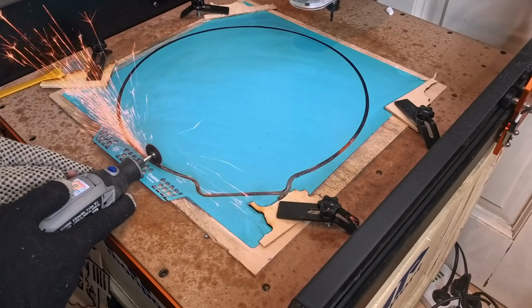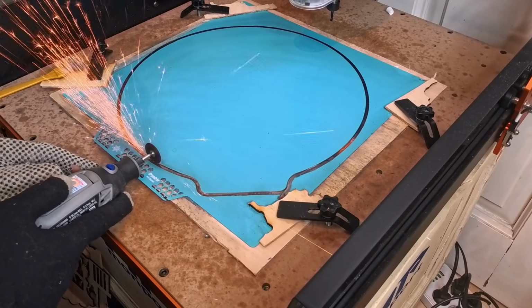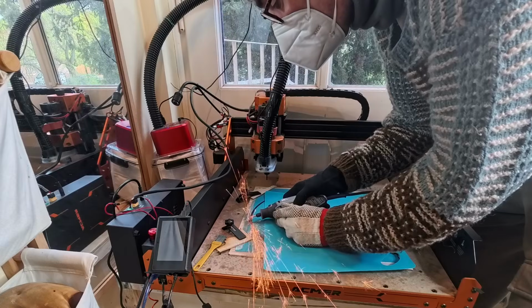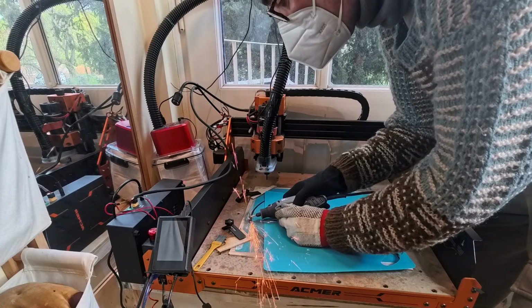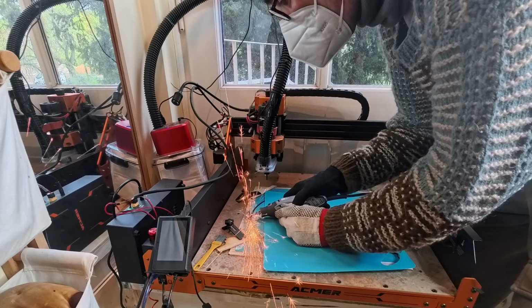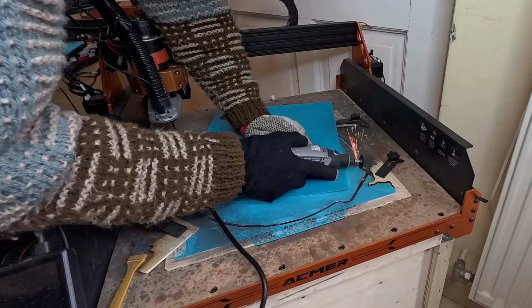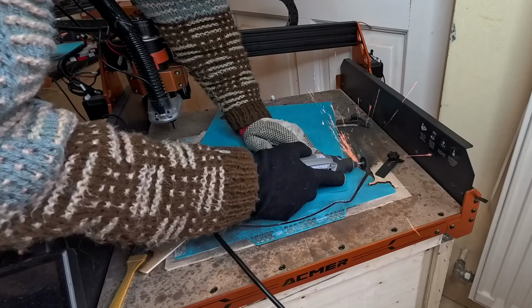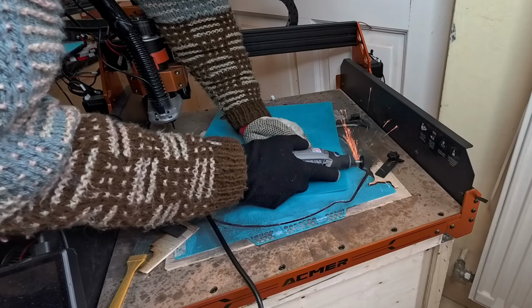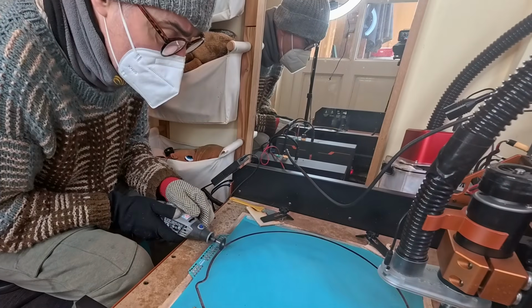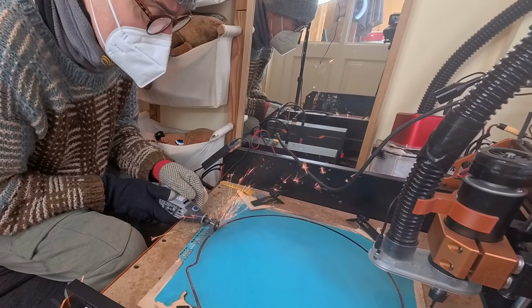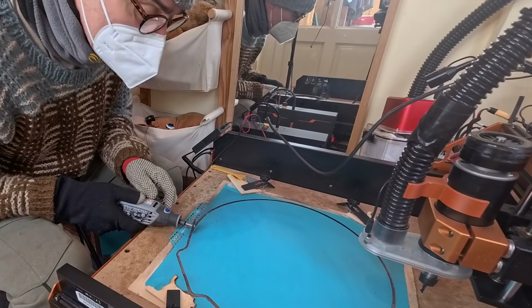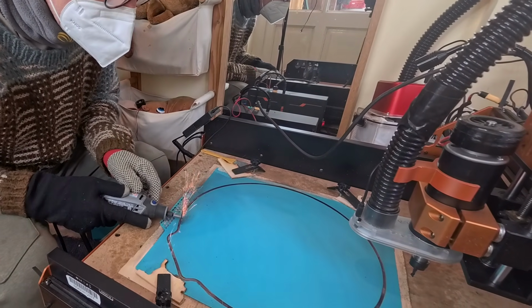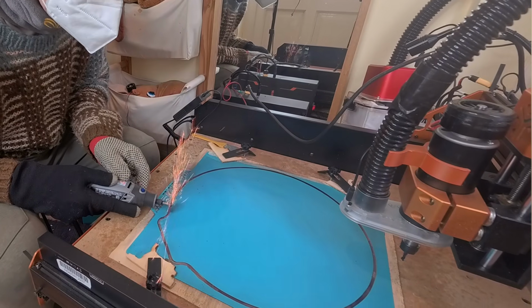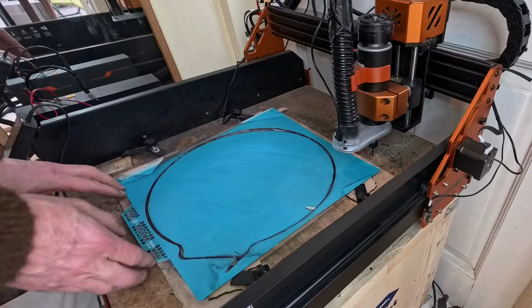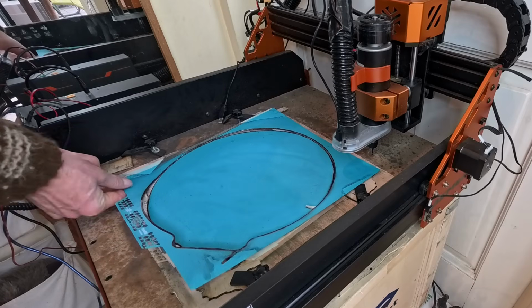I intentionally stayed in the middle of the routed trail, leaving a few millimeters of material along the edge of the circle. Running the Dremel at its highest RPM of 32,000, I carefully worked my way around the circle. You have to go gradually and avoid heating up any one spot too much or you will melt the coating right off the steel. I was fully decked out in a KN95 mask, safety glasses, a hat and heavy gloves because those sparks were flying everywhere. It took about 30 to 40 minutes and I burned through 3 cutting discs on this 330mm diameter plate, but we finally cut it free.